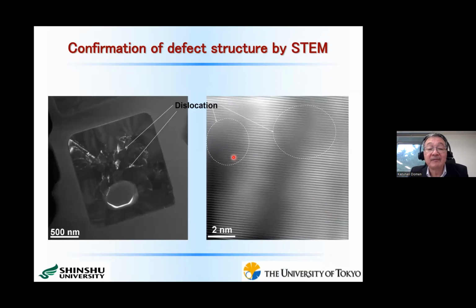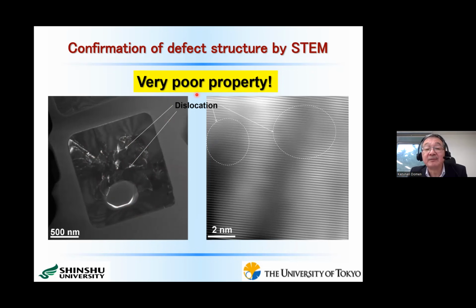However, when we examine these materials in more detail, we realize that this material's property is not so good. This is actually a STEM image of a cross section. And inside of this particle, as you see here, this kind of holes exist. This is not a very special particle, but we very often observe this kind of holes. And this white colored part is actually a dislocation part. So that means that our oxysulfide material property is still very poor.